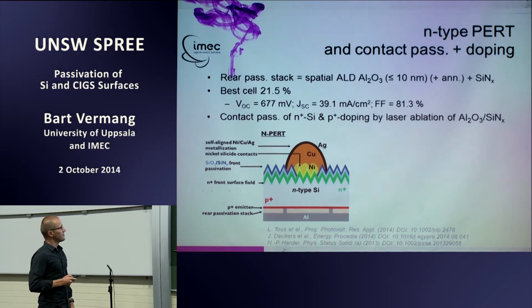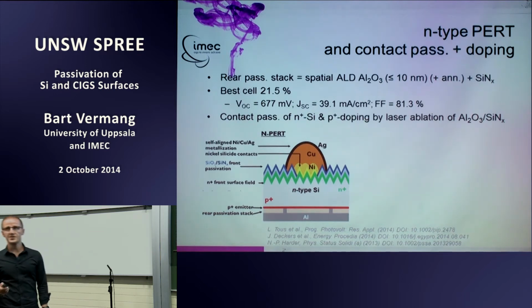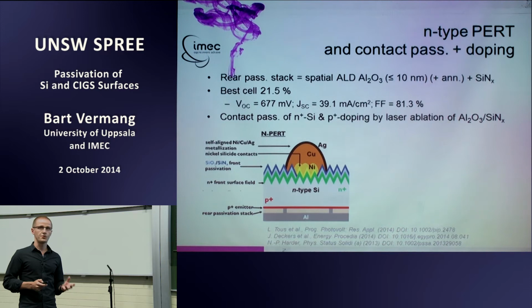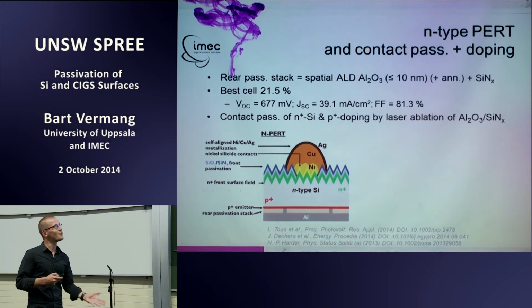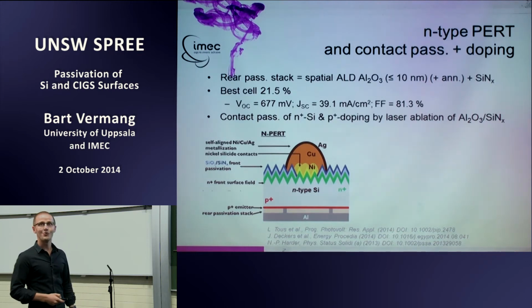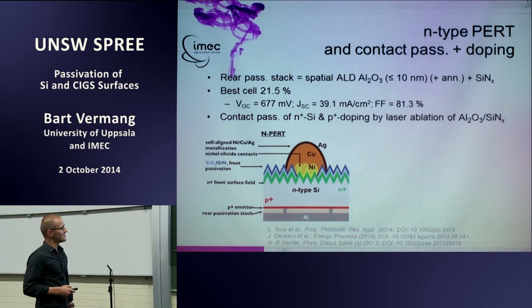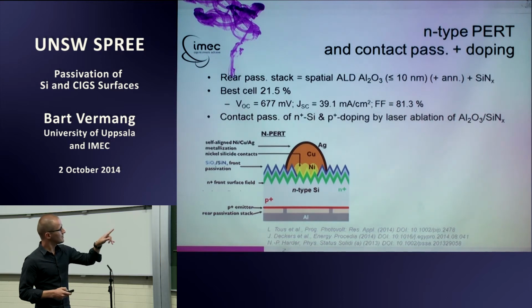Other things they are working on is, for example, you can use ALD aluminum oxide as a source for doping. So if you laser ablate, if you open by laser pulses the aluminum oxide, some of the aluminum will diffuse into the silicon and will give you a locally doped aluminum or a locally aluminum diffused contact. So that's something they have been working on. And also the P+ laser ablation and a contact passivation, of course.